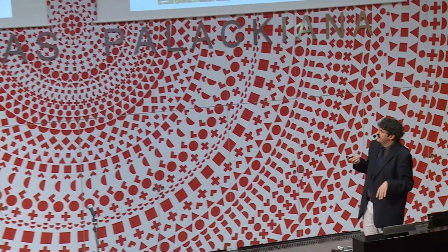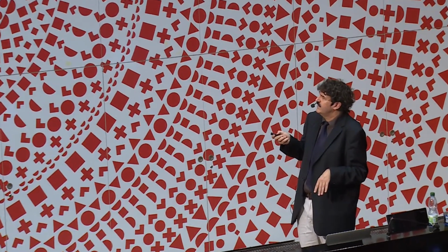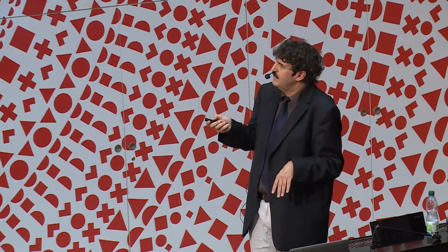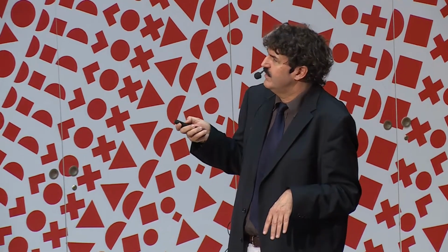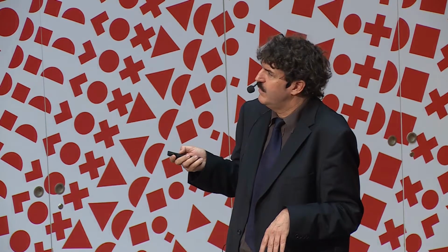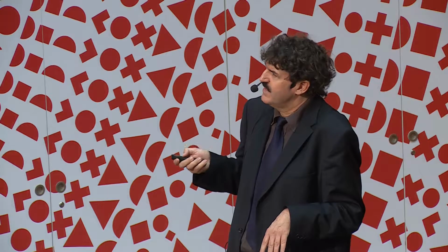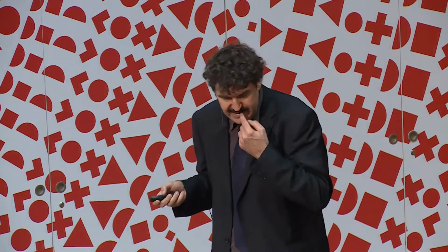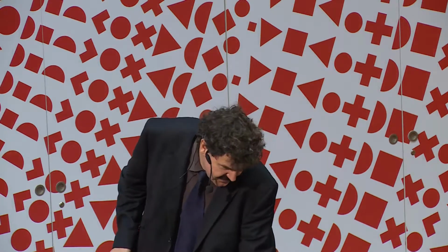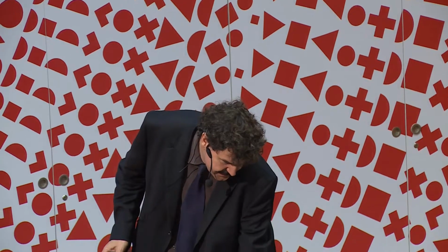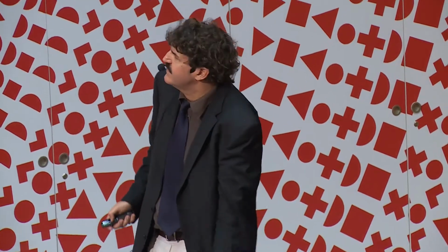After 10 hours you can see already that on the 15 nanometer nanotube surface there are many more cells present than on the 100 nanometer nanotubes, and this is even more significant if you look at the cells at the surface after 3 days.